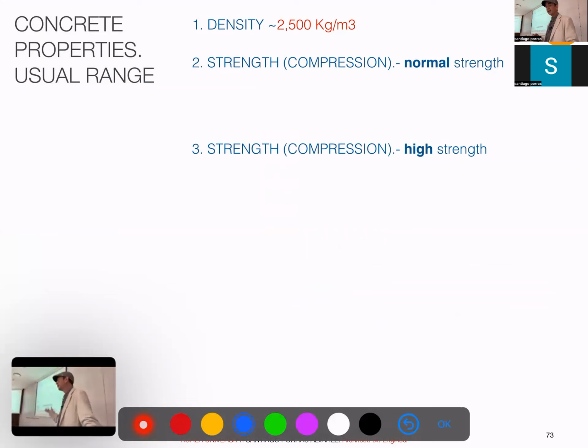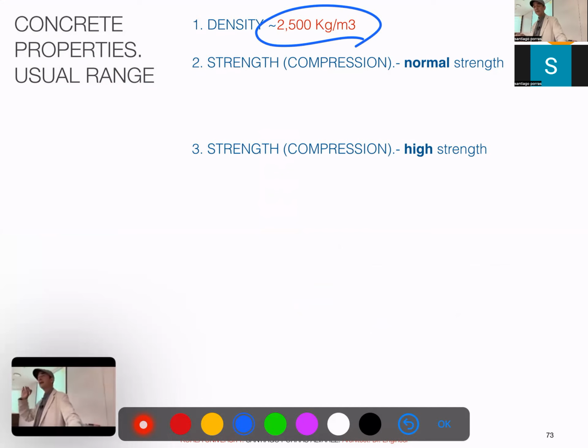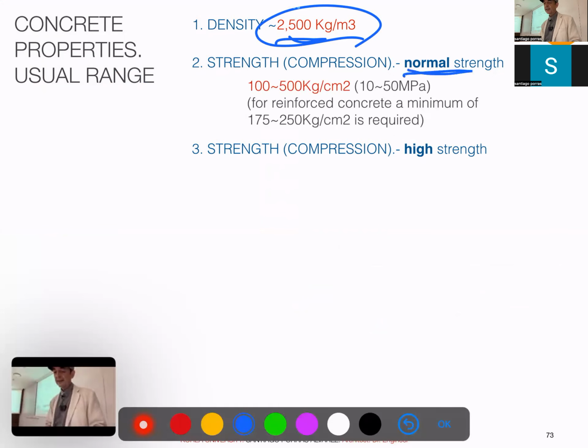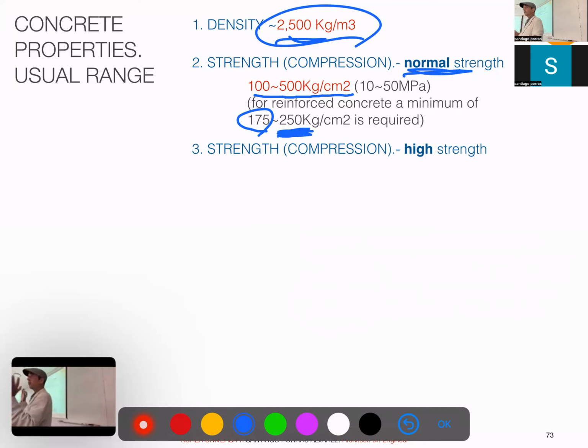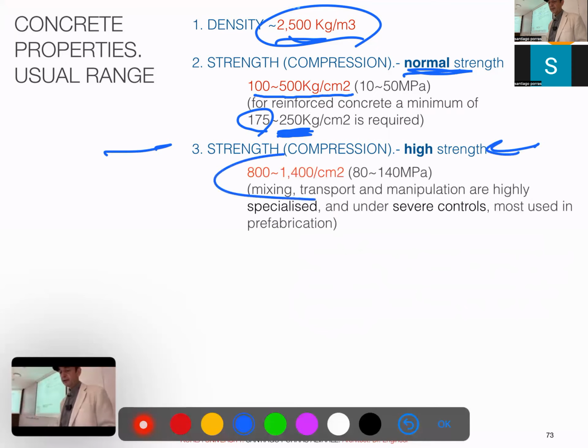Then about the properties. As we said, the density is like the usual stone. It's basically limestone with gravel and sand. The variation will be mostly by the kind of sand or gravel we use, because the stones can change in density. Compression: the usual concrete strength is between 100 and 500 kilograms per square centimeter. For reinforcements, the minimum is 175. But nowadays, I think the Eurocode in Europe considers only concrete over 250 kilograms per square centimeter. I don't know the standard of Korea, but about 200 to 250 is the usual for most common everyday concrete.